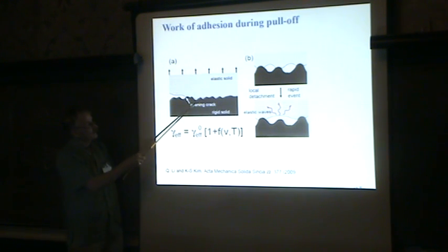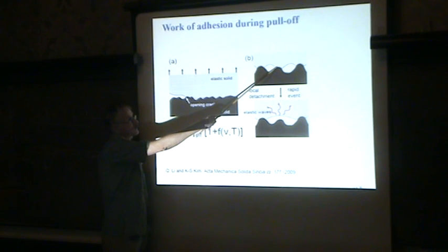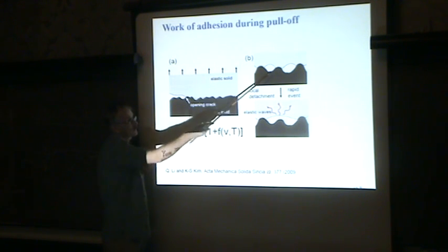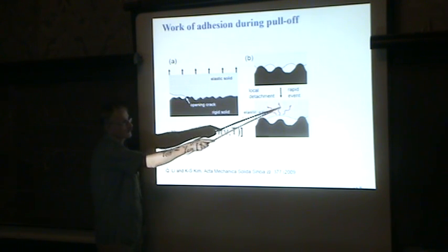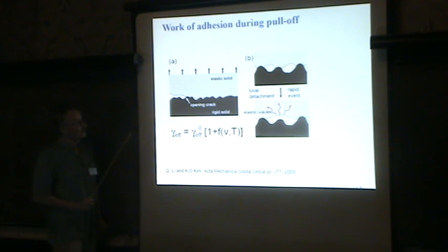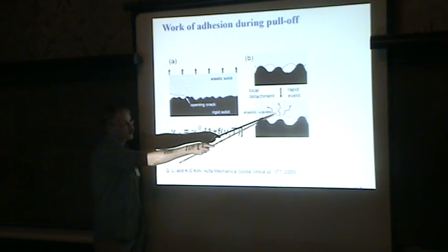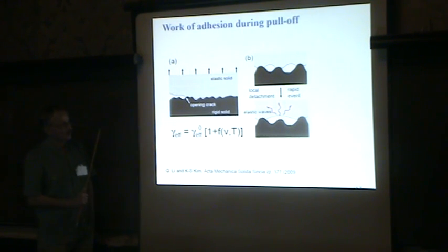And what can happen now is that some asperity contact regions in front of this crack can detach. So if we increase this force, in an asperity contact region where the adhesion is particularly low, the asperity can detach, and this is a rapid snapping motion, and you will get elastic waves emitted. In other words, what I'm trying to say is that the energy to propagate this crack might contain contributions like this, which are not included in the theory I explained before.